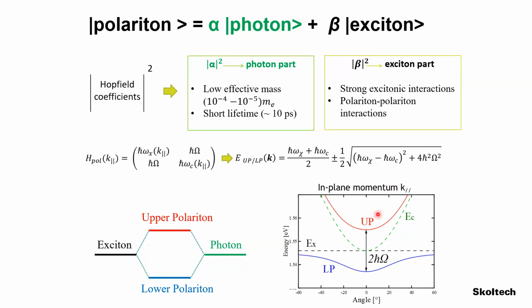Okay, I can play with the resonance between the bare exciton and the bare cavity mode and change the shape of the lower polariton mode. If I go to negative detuning, that is, bringing, for example, the cavity mode at a lower energy than the exciton mode, this lower polariton dispersion will become much deeper. So I can really play with the energy-momentum relationship of the system, with the effective mass of the system very easily, and I can exploit this as we will see later.